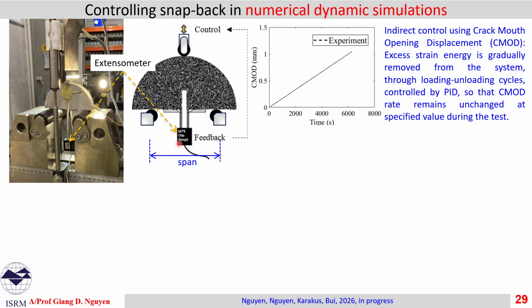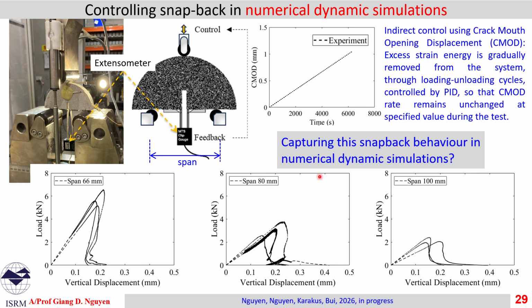In order to do that, we have the feedback here from the clip gauge, giving us the crack opening that is fed back to the control, so that loading and unloading processes can gradually take place, and those loading-unloading cycles will remove the excess strain energy from the system. As a result, if we change the span from smaller to larger, we capture a range of behavior, from very strong snapback to milder and very little snapback if the span is large enough.